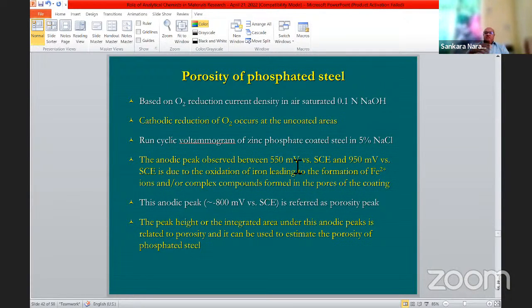When you run a cyclic voltammogram of a zinc phosphate coated steel in 5% sodium chloride solution or something like that, the anodic peak observed between 550 millivolts and 950 millivolts is due to the oxidation of iron, leading to the formation of ferrous ions or complex compound in the pores. Because it is the uncovered areas where the corrosion attack will first occur, as the other areas are covered by the coating. So there will be an anodic peak around 800 millivolts.